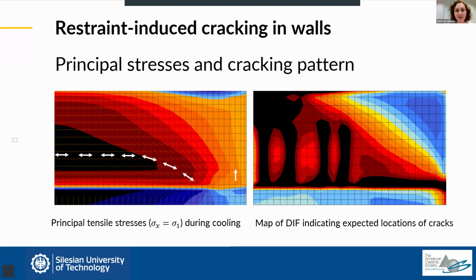And as a result, the cracks look like that. So they are vertical in the central part of the wall. So again, we are looking at a quarter of the wall, actually like a half length of the wall. So what we see here is that the crack in the center of the wall is vertical and reaches relatively the biggest height. And then the cracks become smaller and they turn to tilt towards the end of the wall.